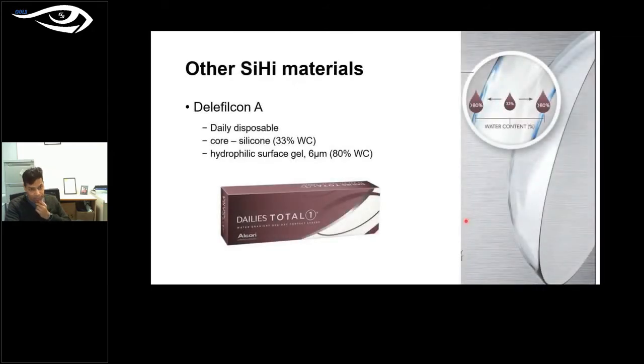There are other types of lenses. I'm sure you guys are more familiar with these lenses, which are Dailies Total 1. This is a daily disposable contact lens, which has two types of material. One is silicone in the central core, and we have a hydrophilic gel on the outer surface, which is about 6 microns in thickness. The outer surface has a greater water content than the core component, which is only 33%. The purpose here is that it retains the benefits of silicone, while also having the benefits of a hydrophilic surface gel, which promotes comfort.